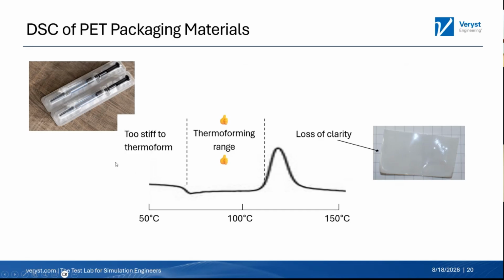And so, which is potentially most relevant to this audience here today, who's interested in thermoforming applications, the thermoforming range for PET means that we need to heat it above its glass transition temperature, but we don't want any of this cold crystallization to occur. Because as soon as we start getting cold crystallization, we get something that looks like this, which is not clear anymore. It's not a nice packaging material that we like.